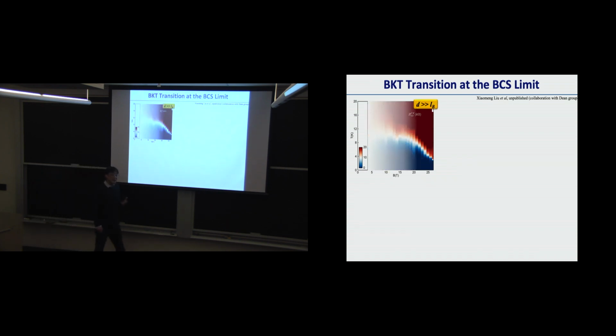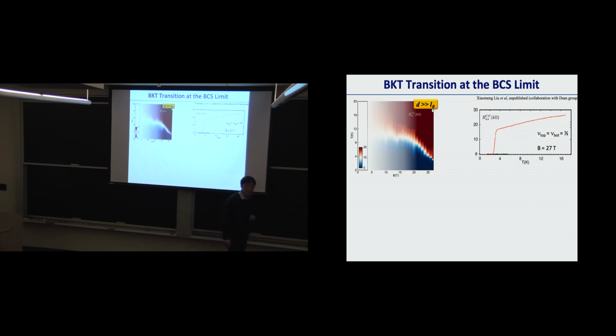In fact, in this BCS subtype of the limits, it has not been well known what type of the wave function I have to write down for this exciton condensation phase, the magnetic exciton condensation phase. But at least experimentally we know that the transition is indeed really sharp.